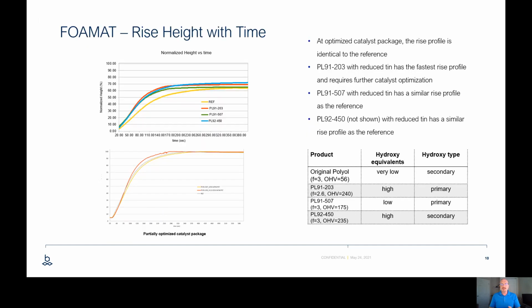Well, one of the first things that we had to do is, of course, make some foam, and we wanted to check to see if our reactivity was acceptable with respect to the foam rise profile. And at first, you can see that the control is a relatively slow foam rise profile. Our materials, when we drop them in, have a somewhat faster rise profile.